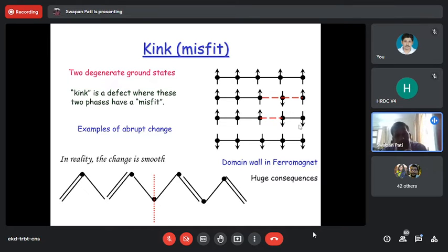That's because it breaks up into domains, various types of domains, because there is an interaction called dipolar interaction. To reduce the dipolar interactions, these magnets break up into various domains and remain in the domain structure. And when you're hitting, one domain becomes smaller and the other domain grows at the expense of the other domain. So a net moment comes up actually, and that's why it attracts. Okay, this is a very different kind of thing. The domain motion, etc., is very similar to the NMR T1 and T2.